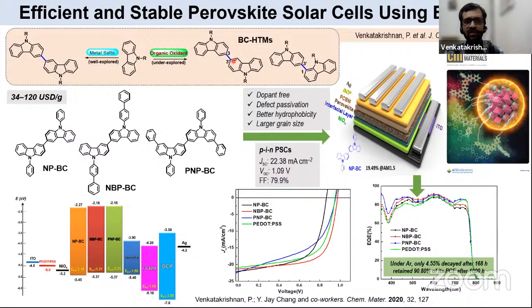We just thought, how can we capitalize on this twisting and fabricate perovskite solar cells and evaluate the performance of these hole transporting materials. Keeping that aspect in mind, we synthesized simple hole transporting materials. You can make them readily in gram scale in the laboratories. When you put them into the perovskite solar cell device configuration, when you use these compounds here, as shown here in orange, red, and green, these three molecules have very convenient HOMO energy levels for the holes to be injected into them.